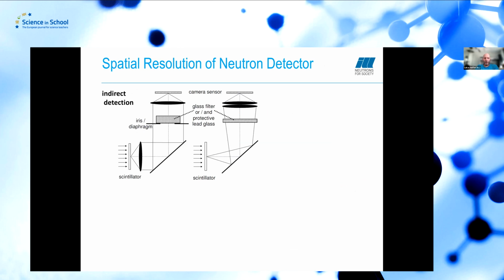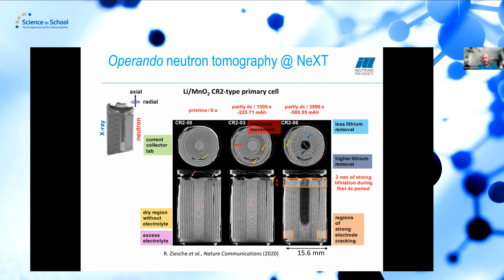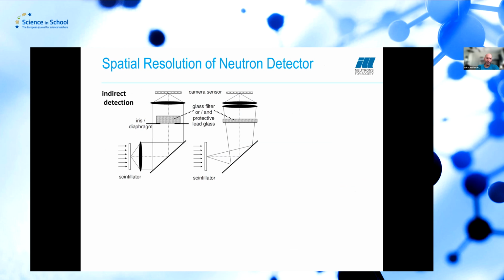If you want to go to higher spatial resolution, so if you want to see, for instance, what happens inside exactly the anode or cathode materials for rechargeable batteries, then you need to really make a good compromise between spatial resolution and temporal resolution. And what we are using at NEXT, and what many other neutron imaging instruments in the world do, they use indirect detection schemes. That means that you use a scintillator material in order to convert the neutrons to visible light. The visible light gets collected by optics via a mirror in order to get the imaging sensor out of the transmitted beam direction. And you have lenses in order to focus the image onto the camera sensor.